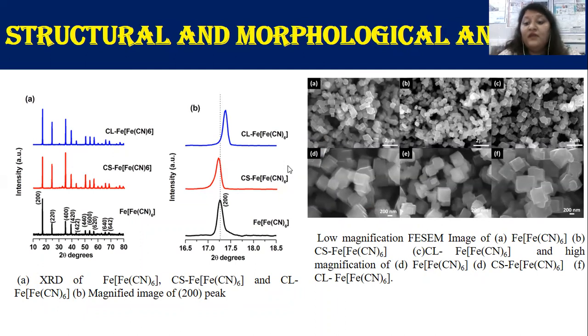FCC space group. And the sodiated Prussian blue analog also has similar crystallinity of cubic structure, whereas the 400 peak becomes stronger relative to the 200 peak intensity, indicating increased local electron density upon sodiation. The lithiated Prussian blue analog also has similar crystallinity to the bare sample, similar to the sodiated Prussian blue analog. It is observed that the 400 peak of the lithiated Prussian blue analog also slightly increased upon lithiation.